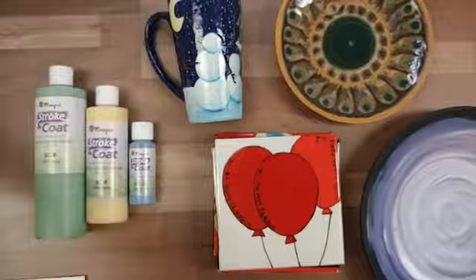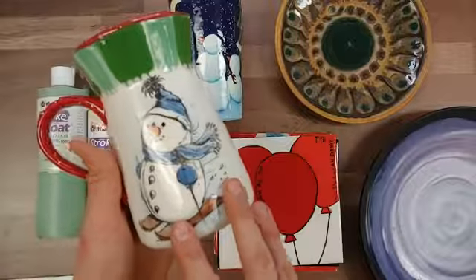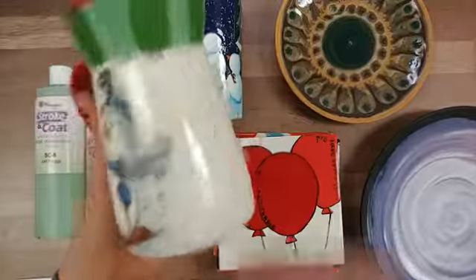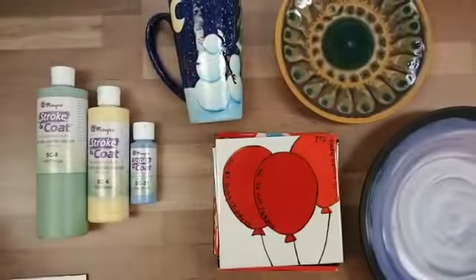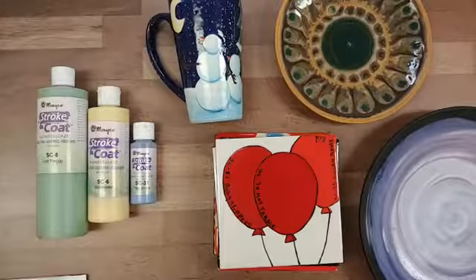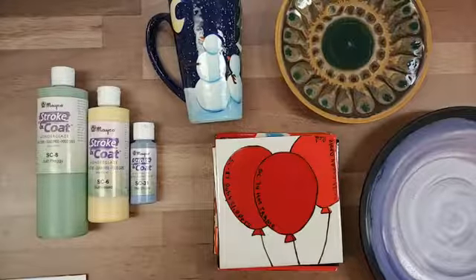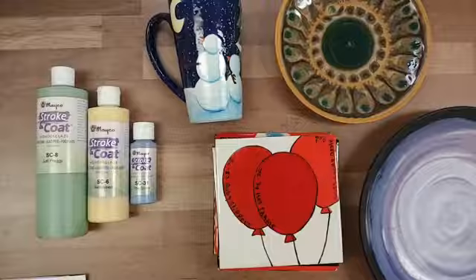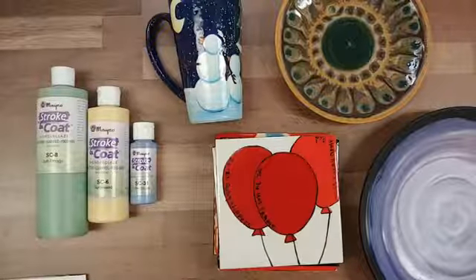Stroke & Coat also works really, really well in design work. So here we're using it with a silk screen, and then just 1 coat. And this piece did have a clear glaze applied to it just to cover up all of these. Some colors are going to react with clear glazes, is one thing to keep in mind. So a lot of the chrome tin pigments, so a lot of purples, those might react, as well as some of the pink colors. Otherwise, you're good to apply clear glaze on top of it.